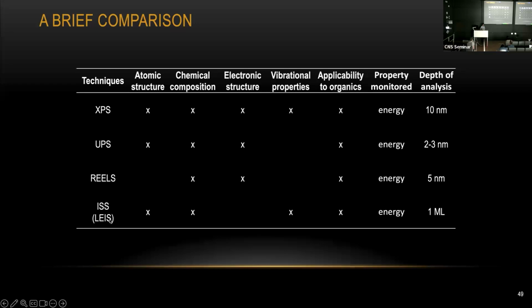For instance, if you try to do some ALD coating, thin film coating on your substrate, and the coating is only a couple cycles, so maybe it's only like 1 to 2 nanometer, we know it's not going to be very uniform on the substrate. So you can try to use an ISS measurement to see how uniform your coating is on the substrate.